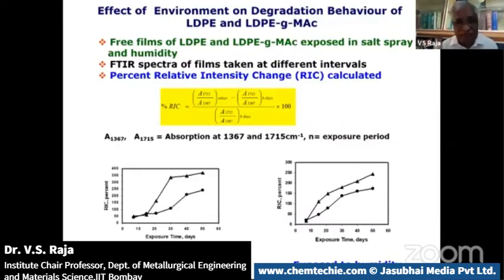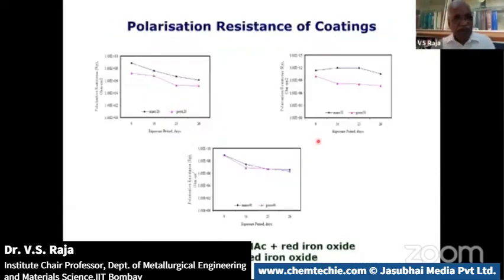You can use various techniques. One technique is IR spectroscopy. We use impedance spectroscopy to determine the amount of water that is being converted into that. We also follow these peaks over here, which are an indication of to what extent the polymer is getting degraded with time. Now, you can quantify the corrosion resistance properties. Look at this value here. We call it the polarization resistance offered by the coating for the flow of current.